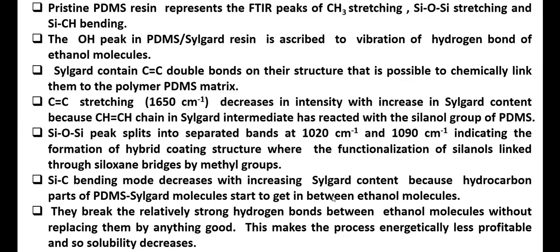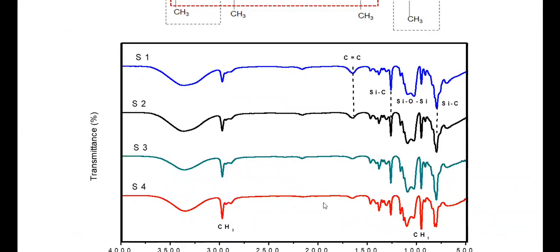molecules start to get in between the ethanol molecules. They break the relatively strong hydrogen bonds between ethanol molecules without replacing them by anything good, and this makes the process energetically less profitable, so the solubility decreases. So this is why the hydrophobicity decreases over here. Okay.